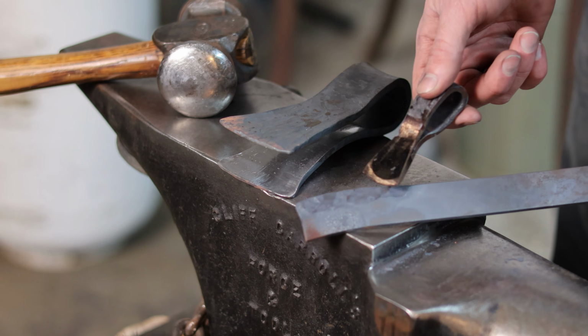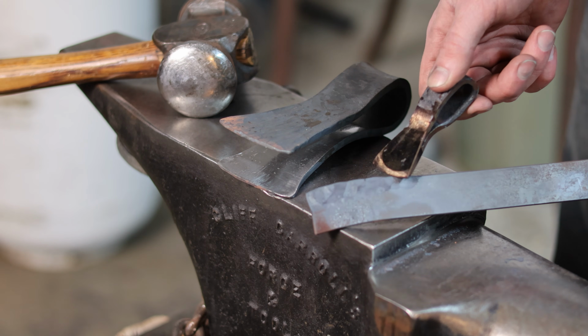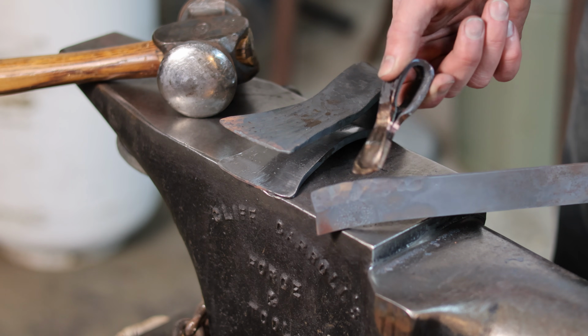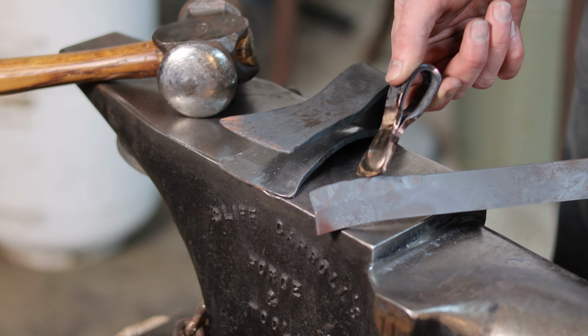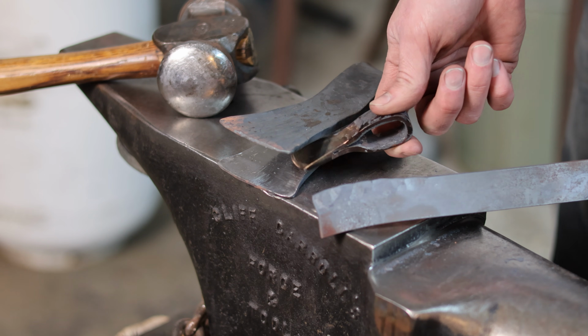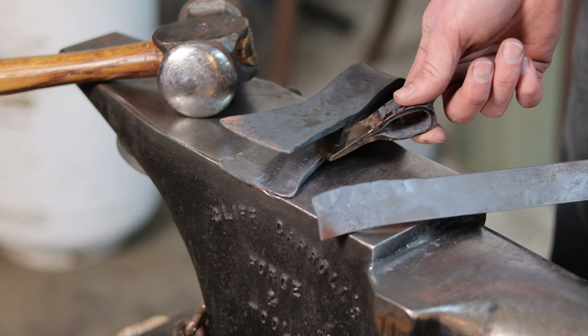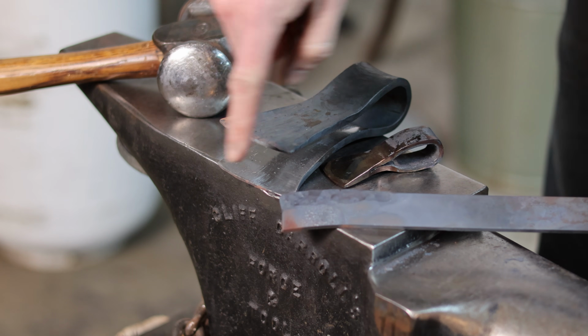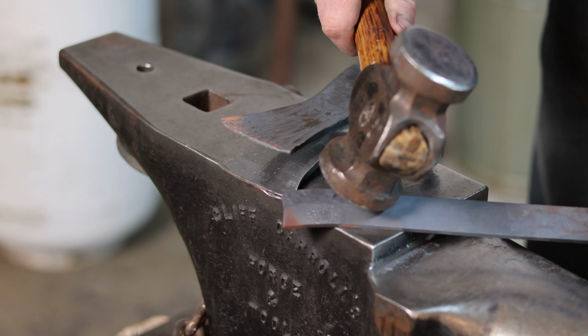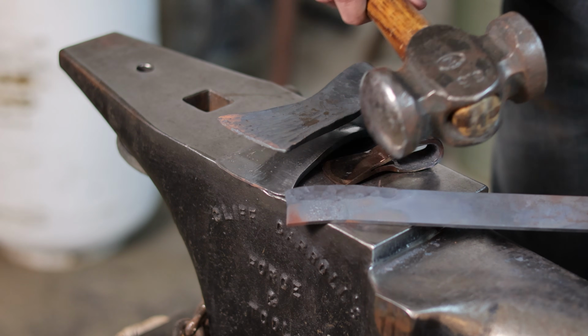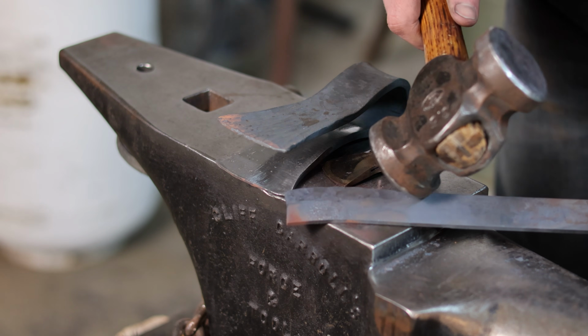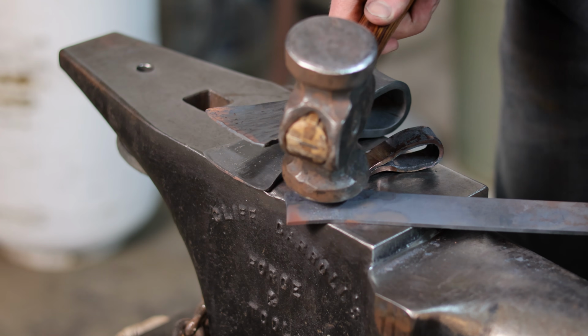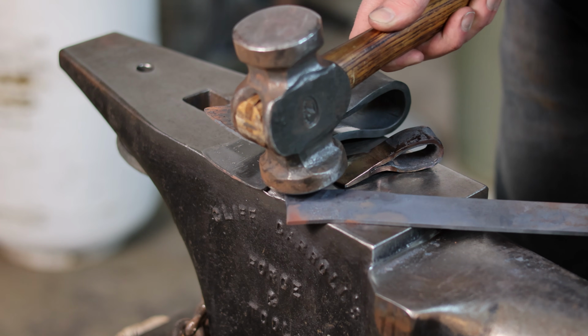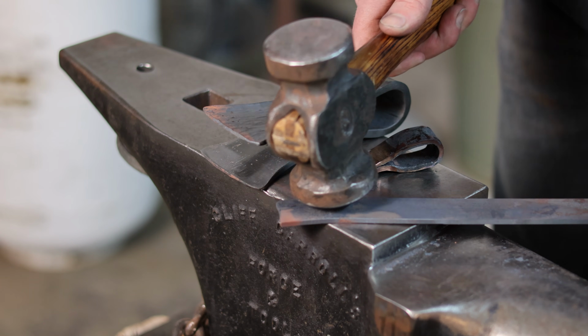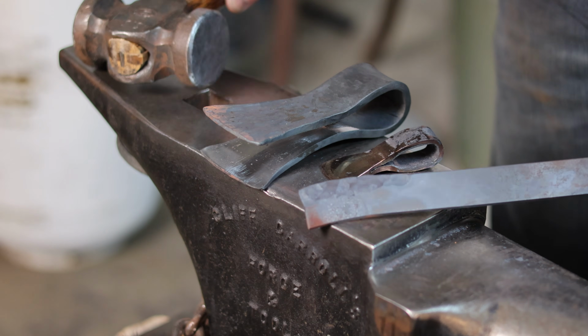So to avoid that, I'm forging down one side about as thin as I can. Not paper thin because that has a potential to burn, but as thin as I can to give it the best chance of forge welding into a complete fused blade here. Now you'll notice that I'm picking up a curve away from the side that I am spreading this on. That's partially because I'm using the rounding face of my rounding hammer, but also strictly because I'm forging on this edge, which is causing spreading away from that. I am going to correct that prior to forge welding this in there.